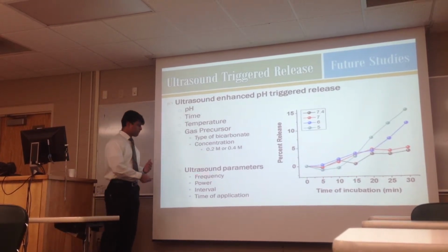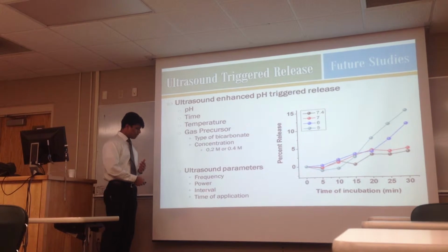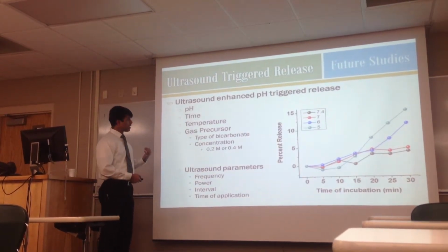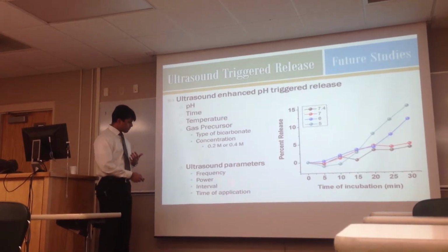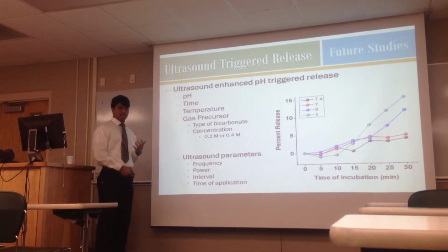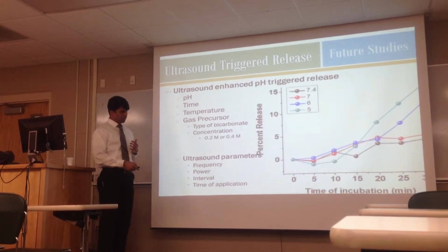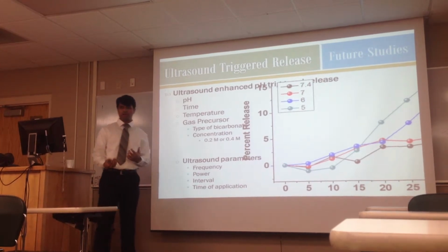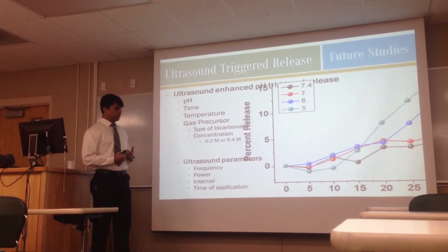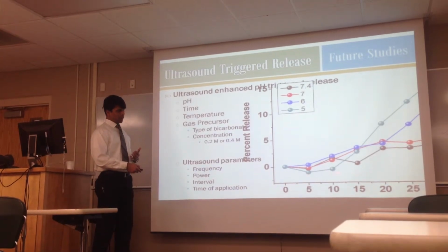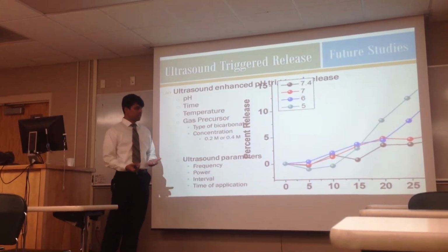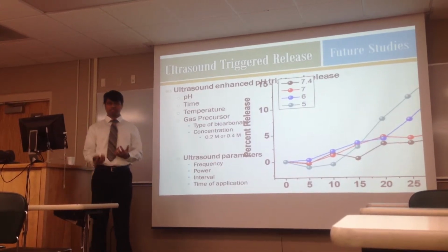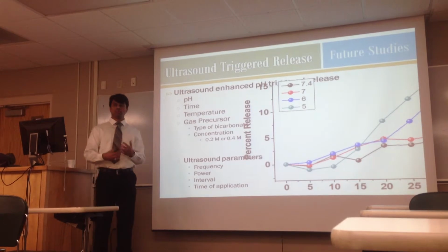We'll also change the ultrasound parameters like frequency, power and interval, and we'll see the effect of these parameters on the ultrasound enhanced release. And the important parameter will be time of application. As I told you, for the initial 10-15 minutes, there is no release from these liposomes and there is a slow production of carbon dioxide inside. So we expect that if we apply ultrasound during this period, there will be no enhancement in the release. And only after 20 to 25 minutes, there will be a sufficient number of bubbles present inside, so that the liposome will be more ultrasound sensitive.